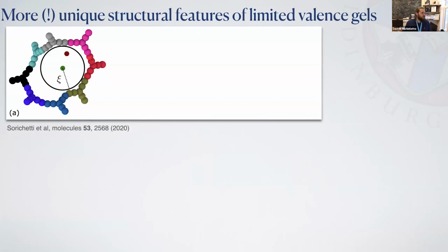So one thing that we started to measure was, for instance, so typically in gels, the elasticity is given by the pore size. So typically you look at the pore size and you say, well, it should be 1 over the pore size cubed in the elasticity, more or less, just as a hand-wavy argument, because it's the density of entanglements essentially that give the elasticity to the material.